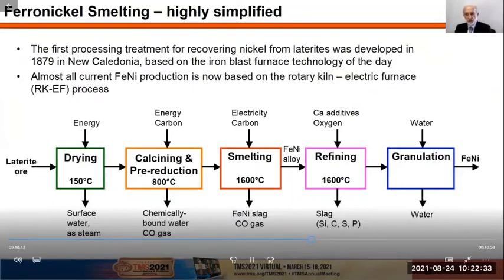The solids are then put into another rotary kiln where energy and carbon, if pre-reduction is to take place, is added, and this drives off the chemically bound water at temperatures around 800 degrees Celsius. The center point of the process is the smelting furnace, operating at about 1600 degrees Celsius, where considerable amounts of electricity and some carbon are added to the laterite ore, producing a molten ferronickel alloy and vast quantities of ferronickel slag, which, it has to be said, contain significant amounts of energy, which is just really an opportunity for people to solve a very difficult problem of recovering some of that energy for the process in time to come.